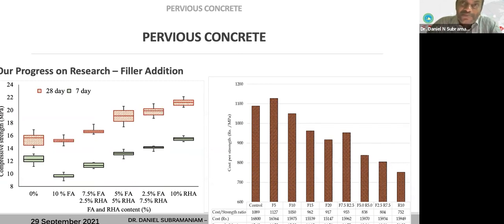Again, another point to note is that these don't have any compaction at all. We have not done any compaction on this concrete with the filler addition. So these are all attained without any compaction, with very high permeability. So there is a lot of room to increase this strength even more, without compromising the permeability. But for this one, we used aggregate sizes of around 8 to 12 millimeters.